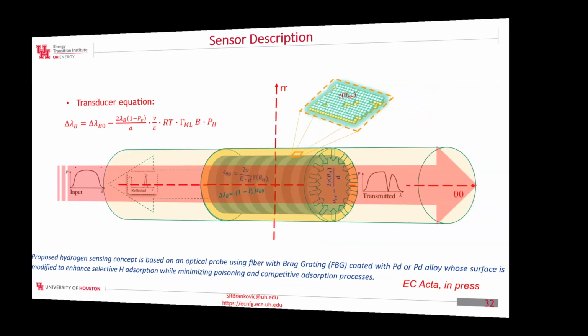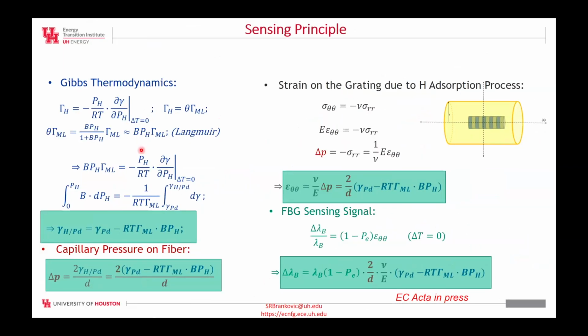in the environment. So the physics behind this is a little bit of thermodynamics. I'm not going to go too much into equations, but the bottom line is that you can see that surface energy of your catalyst coating of the fiber is a function of the pressure of the hydrogen, and the capillary pressure on the grating itself is a function of the surface energy of the coating, which is again a function of the pressure of the hydrogen. Therefore, the strain in the grating is a function of the pressure of the hydrogen, and the shift of the Bragg wavelength is a function of the pressure of the hydrogen. That's the transducing mechanism that supposedly should be operating.